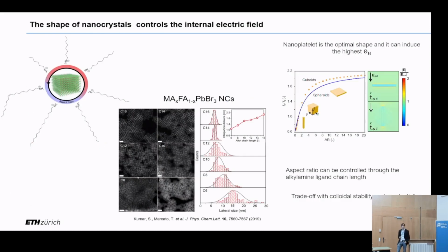So what about the shape? How does shape affect the electric field inside of it? Well, we carried out some simulations and we discovered something interesting. If you take, for example, a nanoplatelet shape where only one dimension is confined with respect to the others, what you obtain is an entity, a nanocrystal, with anisotropic polarizability. In particular, the electric field inside, this is the ratio between the electric field in the plane and the electric field out of plane, you can see it's greater than 1. What that means is that the electric field in the out-of-plane direction, where the nanocrystal is thin, is effectively much more screened than the in-plane one.